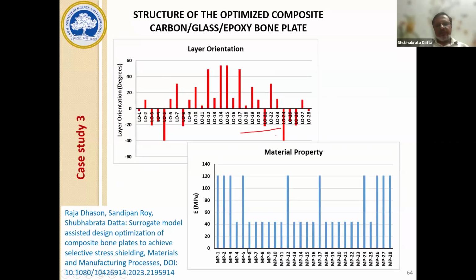Then in that case also, we went for making hybrid composite bone plates with carbon and glass fibers in different layers and in different orientations. That exact testing, in that type of loading condition, we could not do, but we have done the general tensile strength, compression strength and flexural tests. And we have found that at least we have got a material which has a lower elastic modulus, which is reflected in its composite compression and tensile testing, but it has a better improved flexural modulus, which implies that in the shear direction it will behave in a better way.